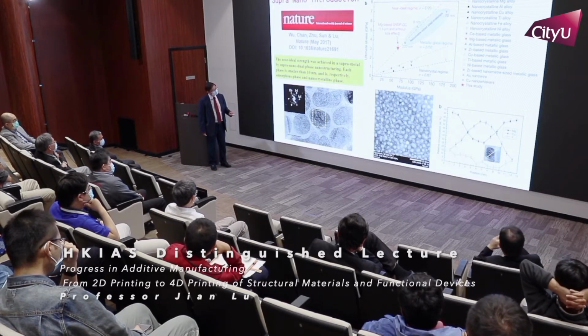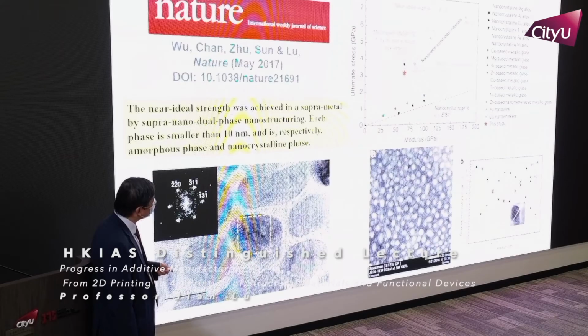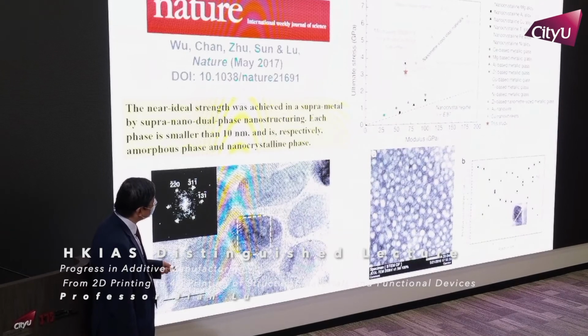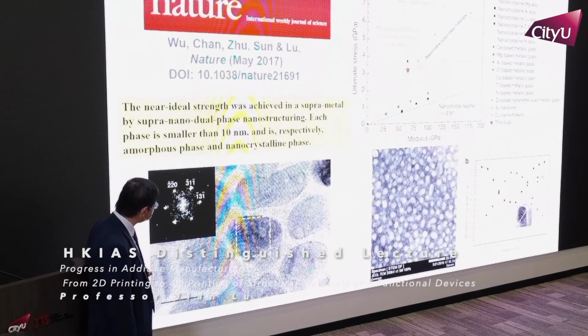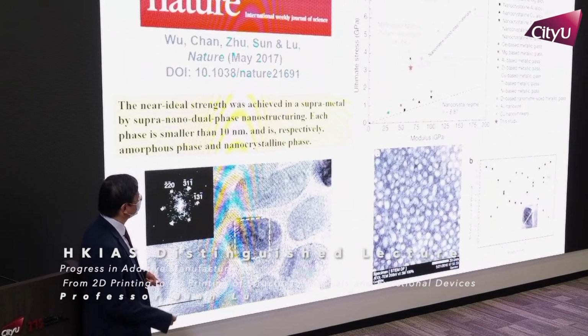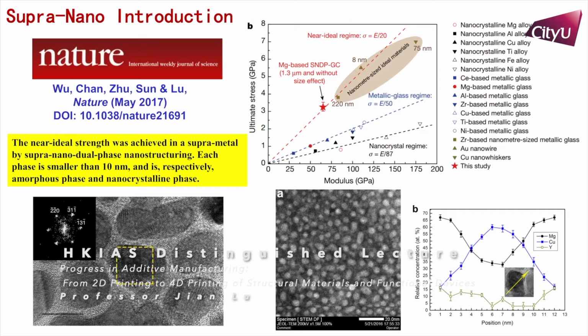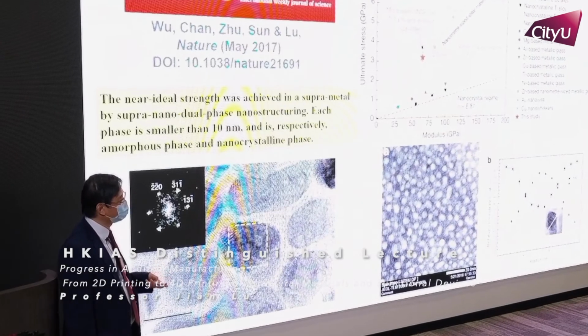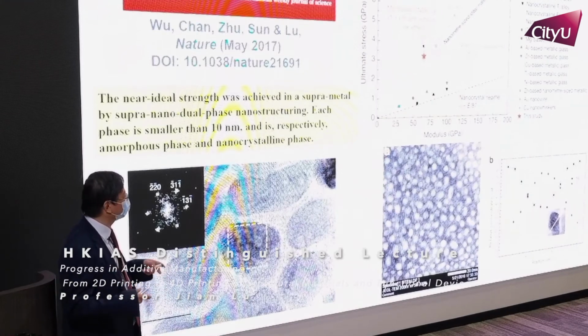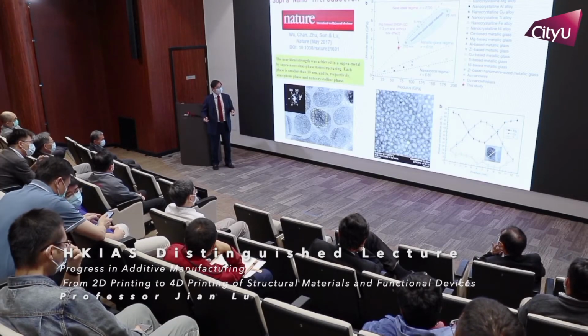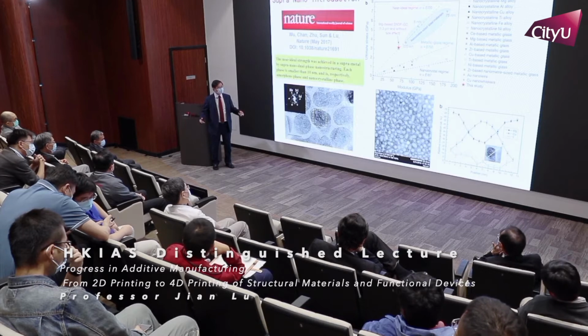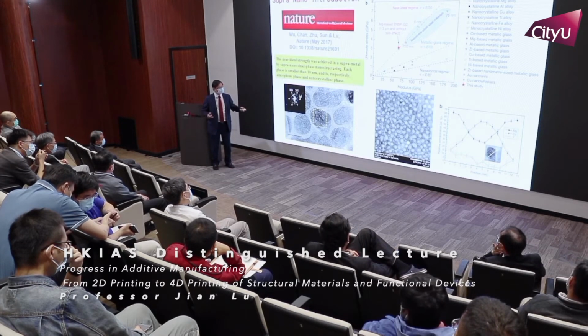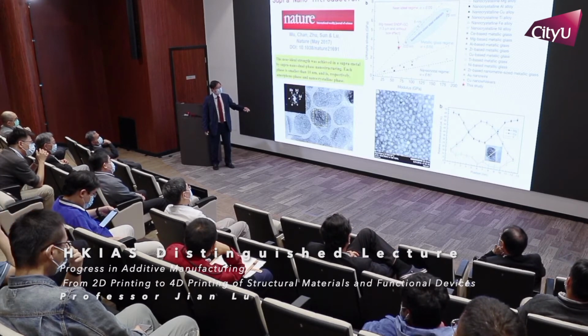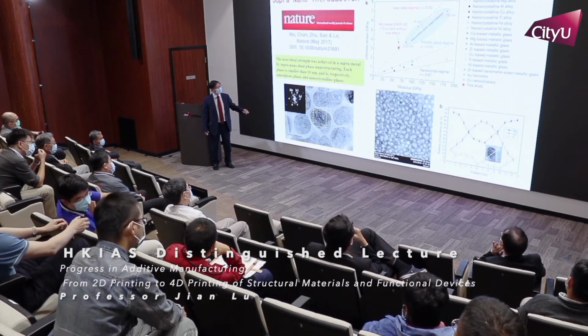If we do the chemical composition analysis, we can see at the center, in this crystal, we have a copper-rich crystal, and outside is magnesium-rich amorphous material. So basically, we need to have two materials, and during the processing, we have a phase separation, and the two phases are distributed equally and homogeneously inside the structure.